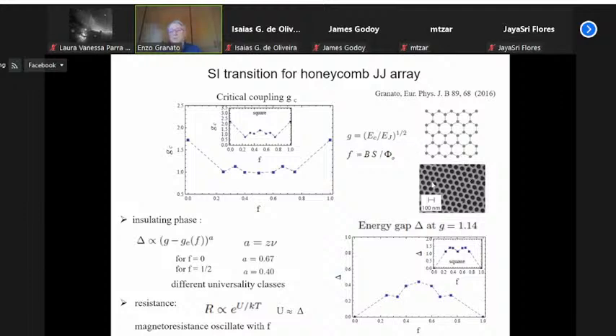If the system is a triangle array of holes, it will be a honeycomb lattice. If it is a square array of holes, it will be a square lattice. We are interested in particular in the measurement done for this system here, which shows some interesting results. The calculations for the critical coupling for the transition are shown here. You see that there is strong dependence on frustration. The critical coupling is larger for zero frustration and for integer frustration.